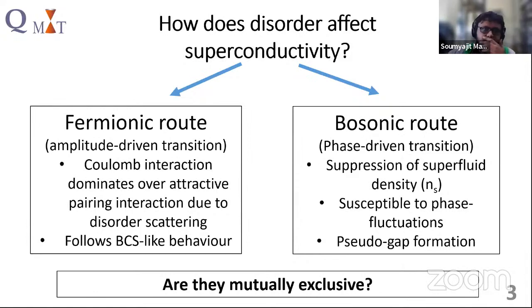Let us first see how the disorder affects the superconducting transition temperature, or Tc. It can have two origins. In case of the fermionic route, what happens is that the Tc is suppressed in presence of disorder scattering, because repulsive Coulomb interaction dominates over the attractive pair interaction. And here the superconductivity parameters more or less follow the conventional Bardeen-Cooper-Schrieffer behavior.